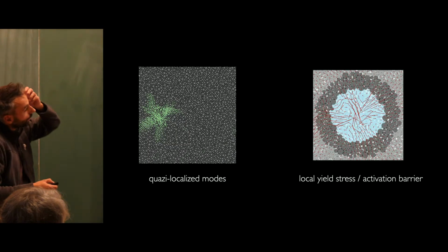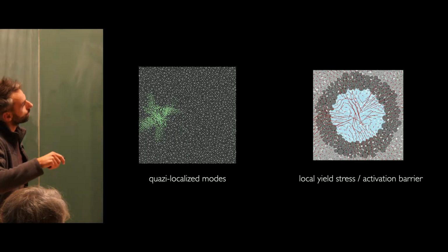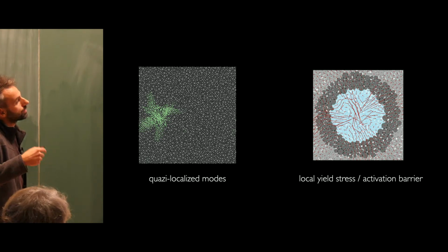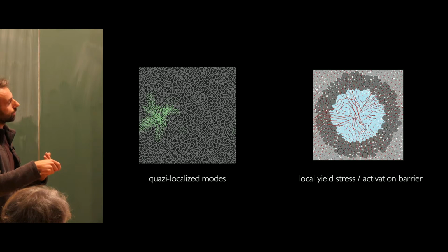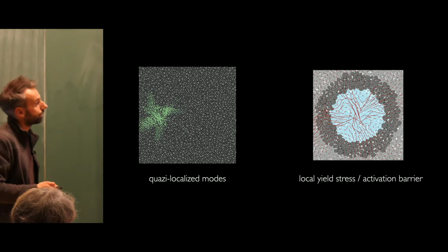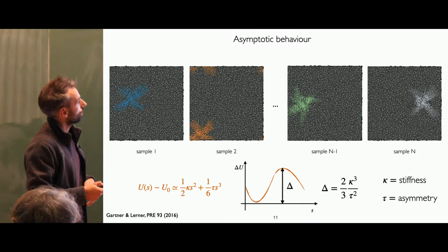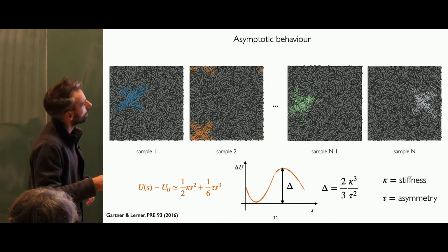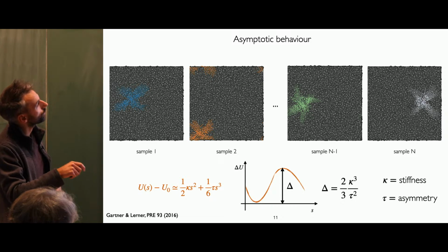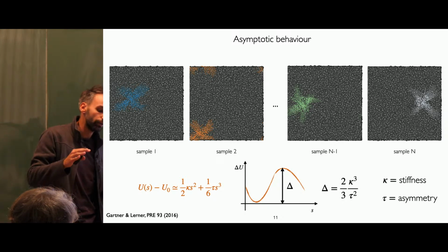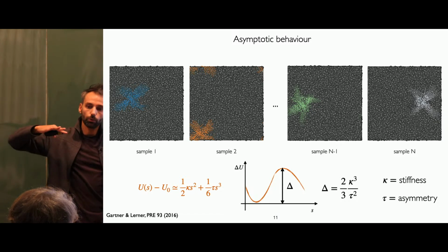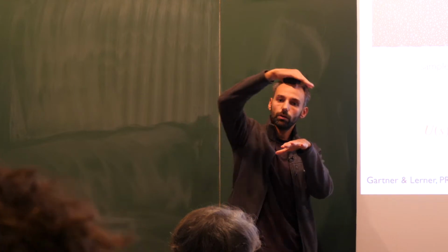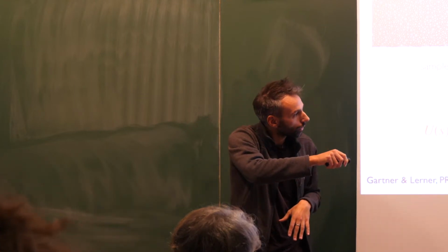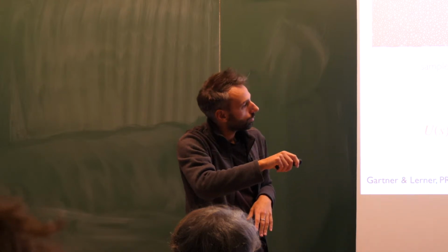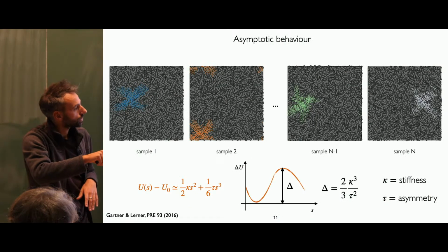Okay, so one of the things that I wanted to do is to try to make a quantitative connection, at least in the limit of soft defects, between my soft mode in my system, my quasi-localized mode, and local yield stress or activation barrier. So one thing that we can do with our method is to ask the following. Imagine I have an ensemble of glasses, and in each glass I'm going to try to find what is the excitation that, if I push my system along it, will move me across a barrier with a high delta. I can do that by both minimizing the stiffness of the mode and maximizing its asymmetry.